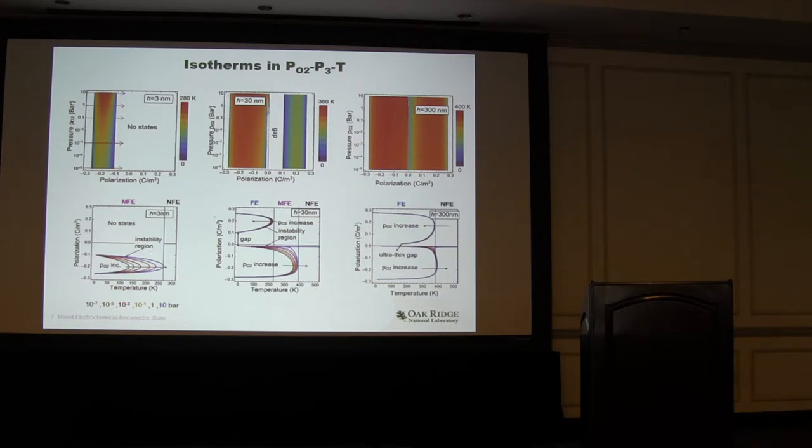One of the solutions is unstable, and the only one with the values related to the spontaneous polarization is stable. So clearly here, we only find a mixed ferroelectric state and a non-ferroelectric state. Here, when there's no solution, we define it as the non-ferroelectric state, with only one solution ascribed to the mixed ferroelectric and chemical state.